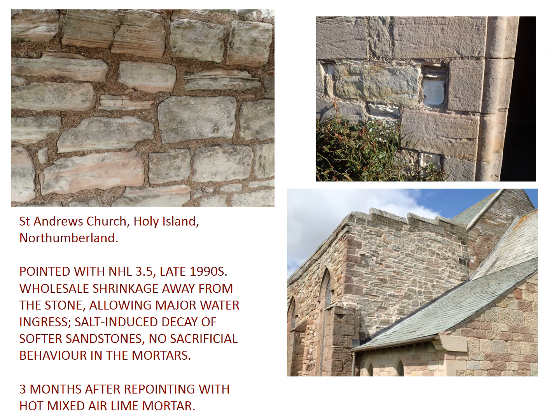Another issue we see commonly with NHLs is shrinkage away from the stones, indicating a poor initial bond, but also indicating ongoing shrinkage potential after the mortars have become hard. This wall is absolutely saturated, green with algae on the inside leaf. And equally outside, in places where there are salts in the equation, we see the degradation and disintegration of the weaker Pennine sandstone. Bottom right, a repointing done by ourselves with a hot mixed air lime mortar. This is 3 months after that, but that's because we only went back after 3 months to see it.